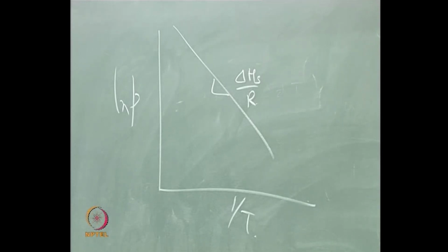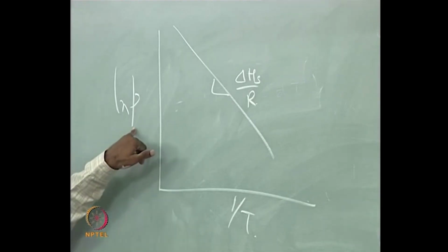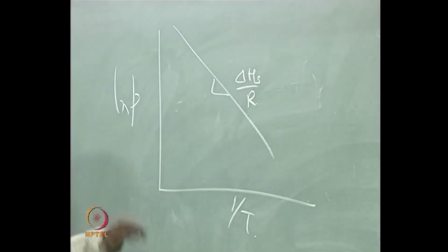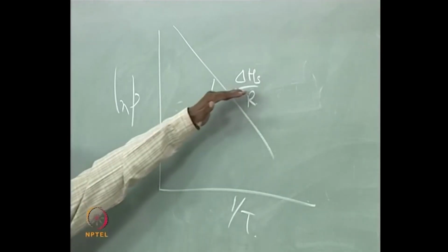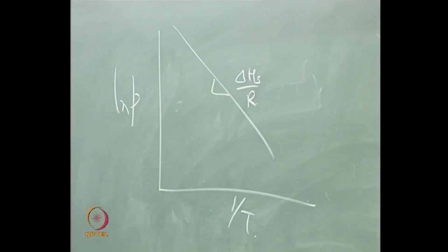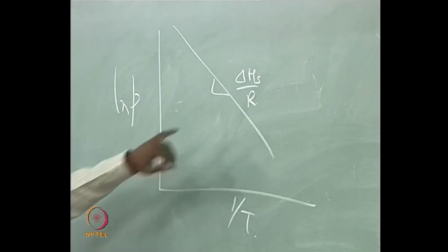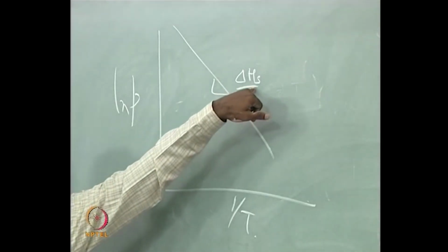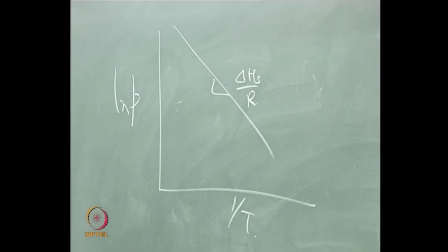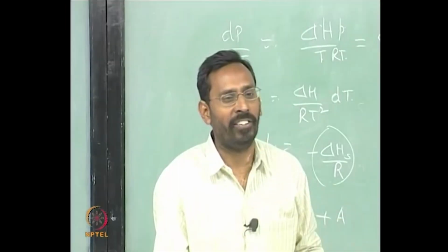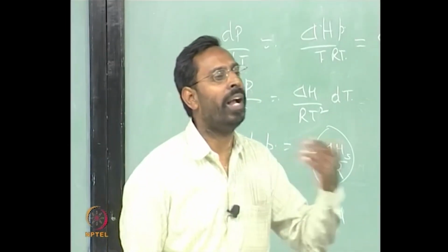So you need to provide more energy for the sublimation to take place, for any solid molecule to be converted into a gaseous molecule. So if that is the case, the partial pressure of the gas that is generated at any given temperature is going to be proportional to that, inversely proportional in principle. So as a result we can say that whenever the sublimation enthalpy is higher, this is also similar to saying that whenever the heat of fusion is very large, the metal to melt is more difficult,